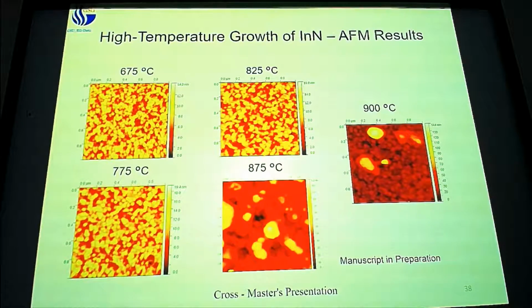We have the Raman peak to show that it's indium nitride, but it doesn't look very nice. And I mean, it still doesn't look very nice out here either. But as we start getting out here, we start getting larger structures. And we believe these larger structures are what lead to that E2 high peak. So we have a larger crystal, which we can actually measure as a distinct material away from this granular background. So that's what we think.